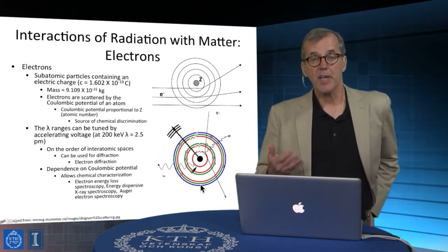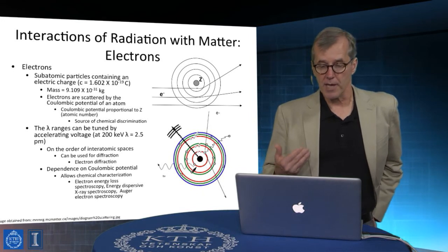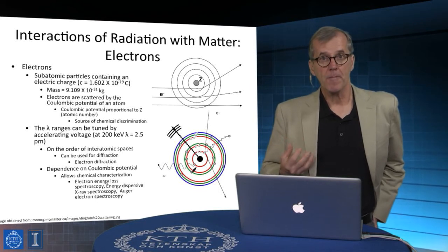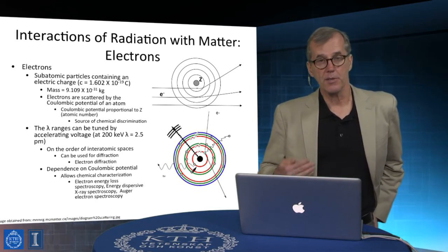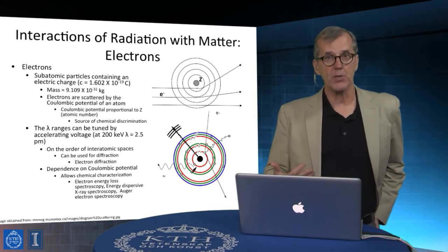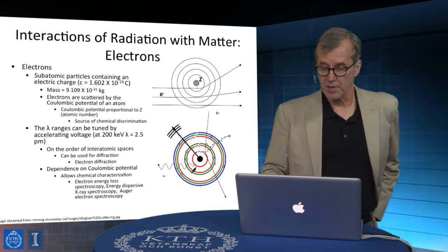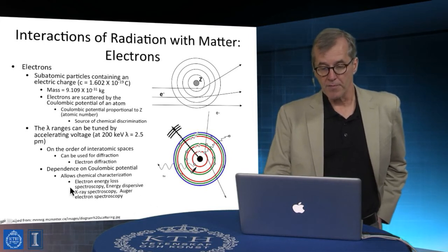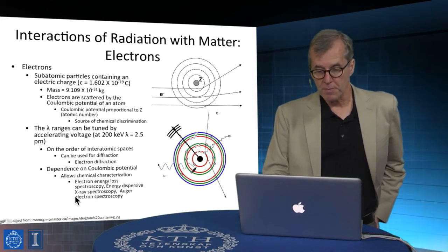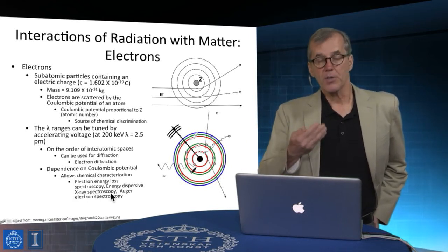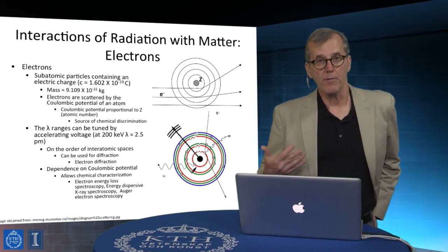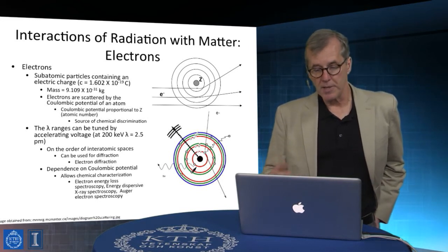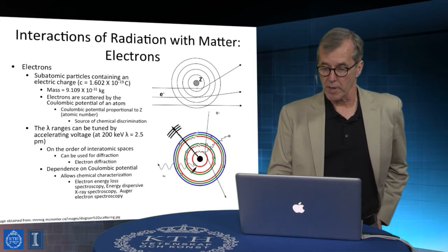And again, these secondary processes also provide a capability for doing characterization with transmission electron microscopy that would allow us to deduce things not just in terms of atomic positions, but also chemical identities. And we'll explore these ideas in a little bit more detail. So, for example, via electron energy loss spectroscopy or X-ray emission, we can actually do fairly important and useful forms of characterization of electronic structure and chemical composition and bonding states directly in the electron microscope.